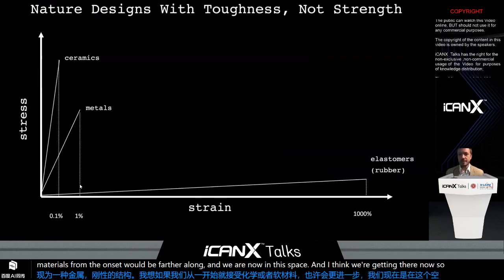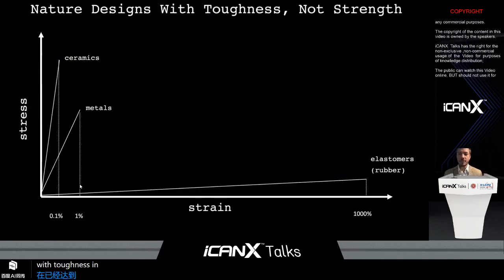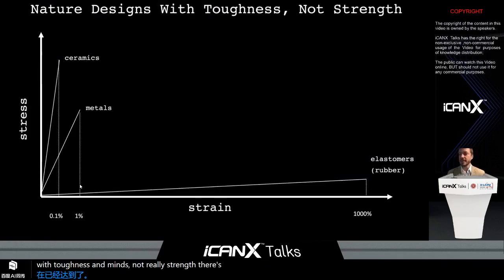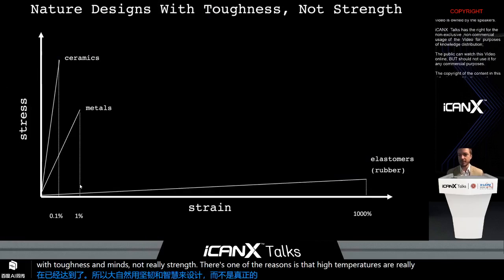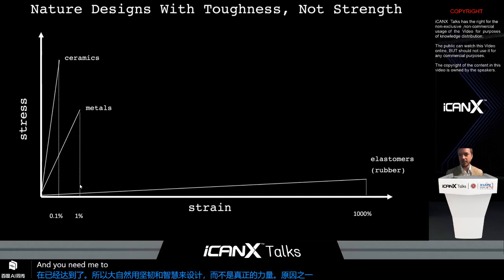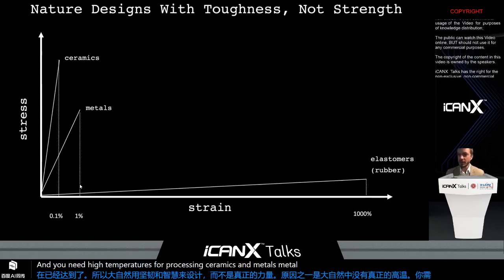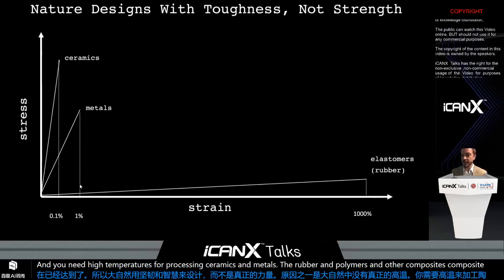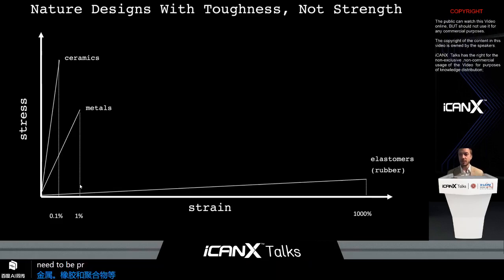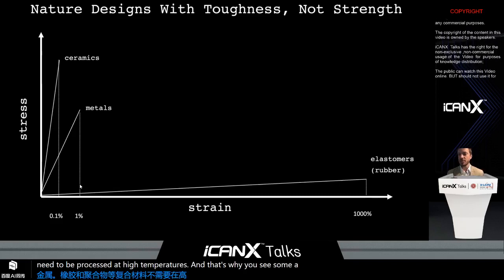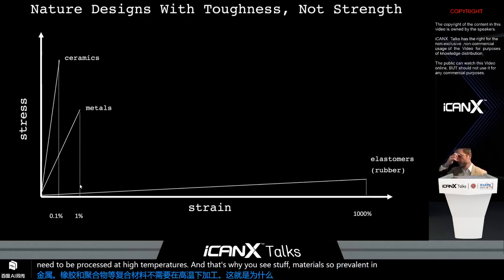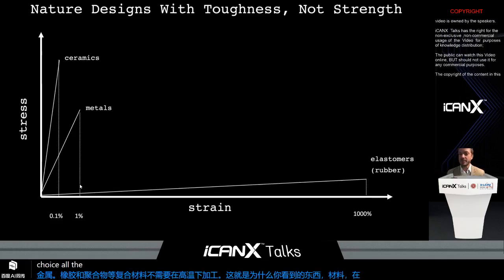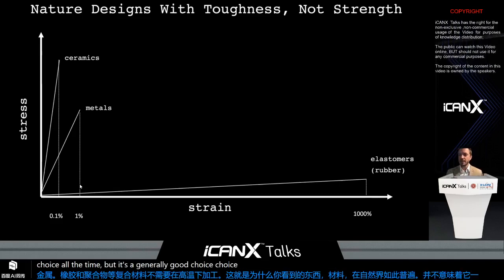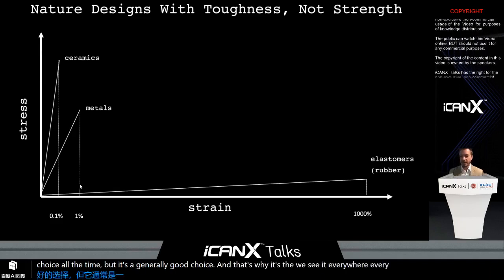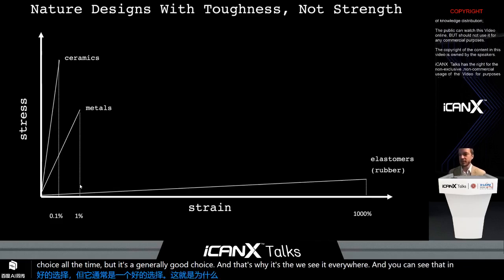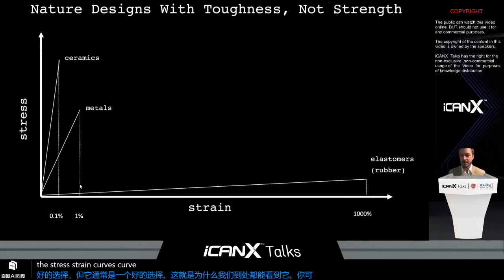So nature designs with toughness in mind, not really strength. One of the reasons is that high temperatures aren't really available in nature, and you need high temperatures for processing ceramics and metals. But rubber and polymers and other composites like that don't need to be processed at high temperatures, and that's why you see soft materials so prevalent in nature. It doesn't mean it's the best choice all the time, but it's a generally good choice, and that's why we see it everywhere. And you can see that in the stress strain curves of ceramics, metals, and rubbers.